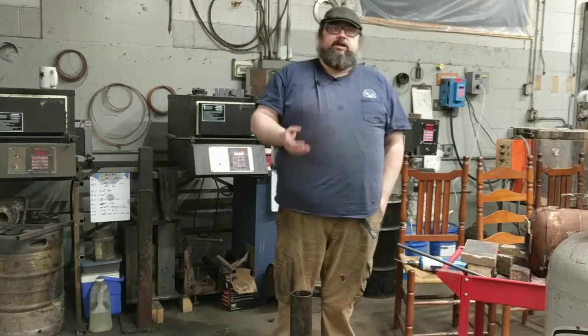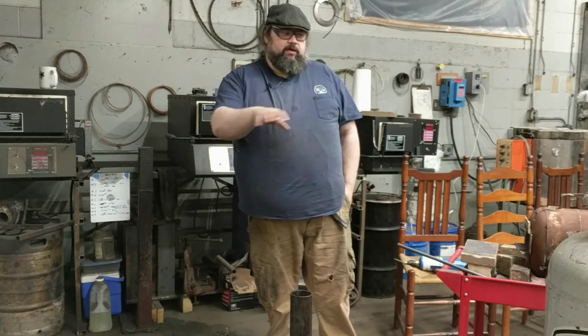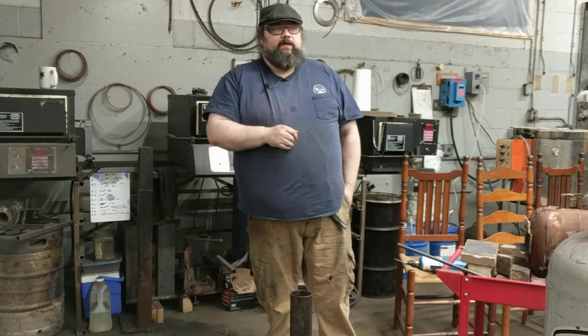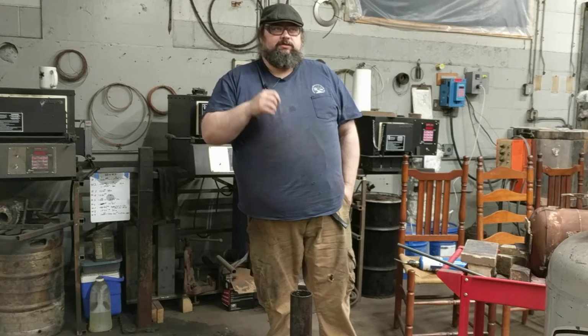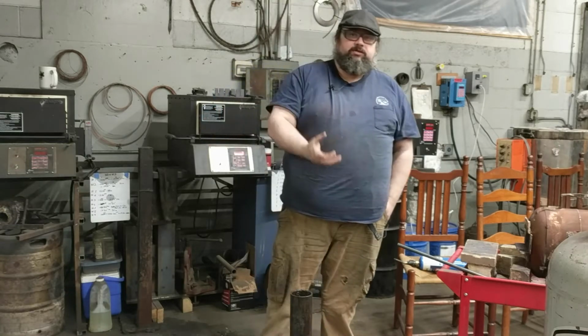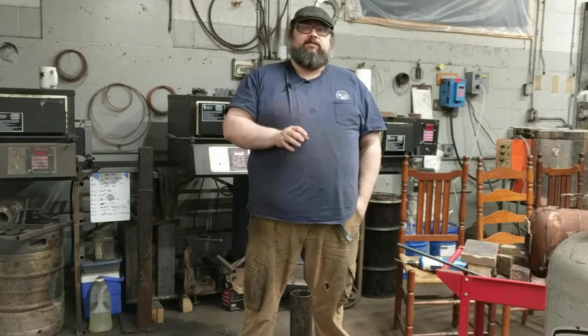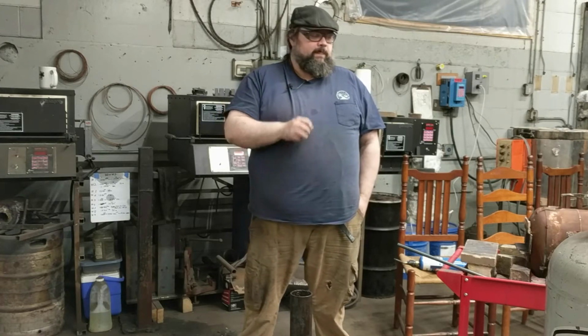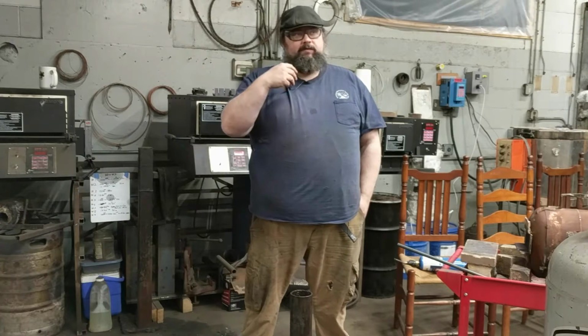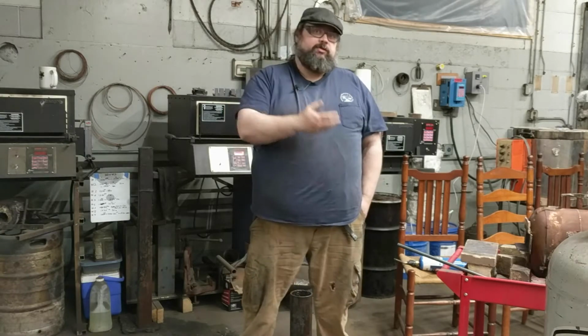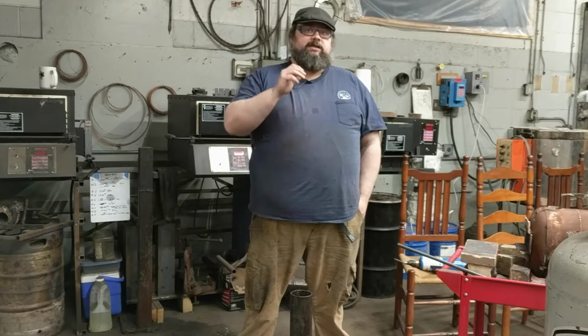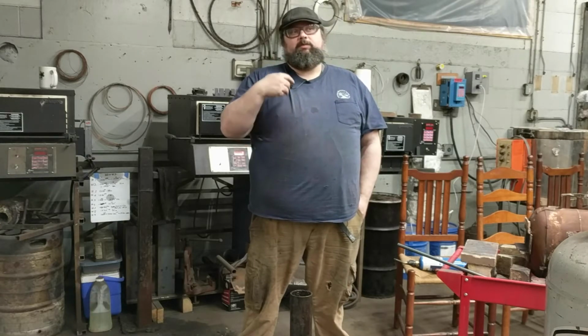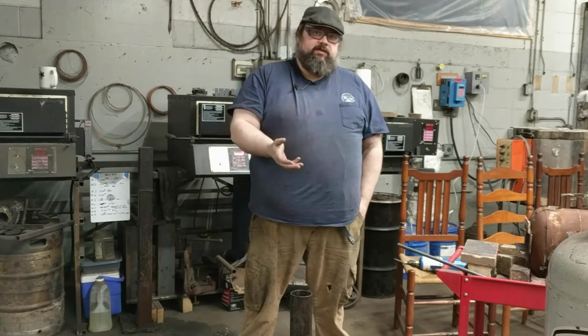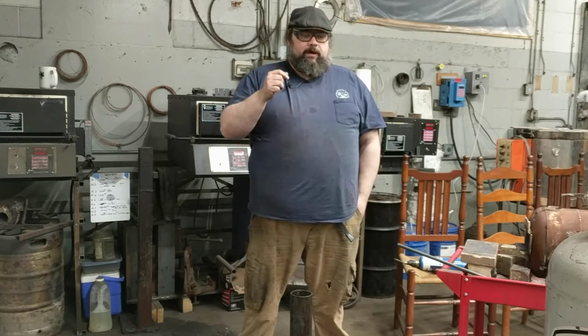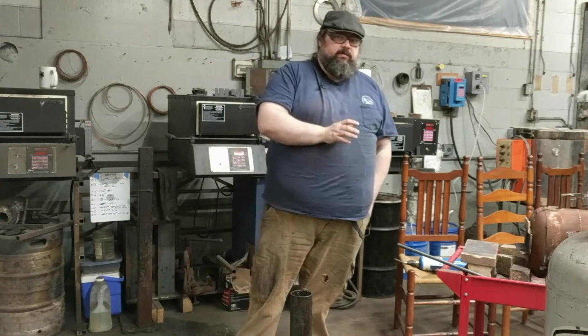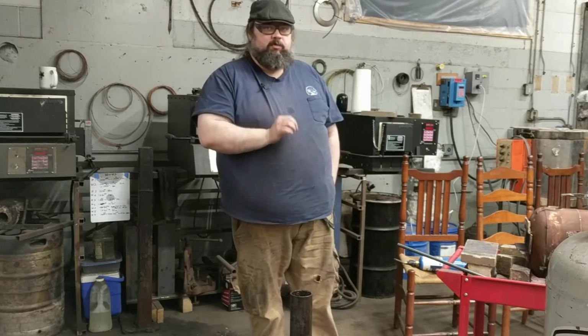If we're using 1080 or 1084 or anything around that mark, 1060, generally speaking, those steels austenitize, or reach what we call critical temperature, right around 1450 to 1475. Steels that have a little bit of chromium in them, things like 80CrV2 or 5160, tend to austenitize slightly higher. So the critical temperature will be around 1550 or 1575 even in some cases. That isn't to say that they won't harden from a lower temperature. You just won't get optimal performance.